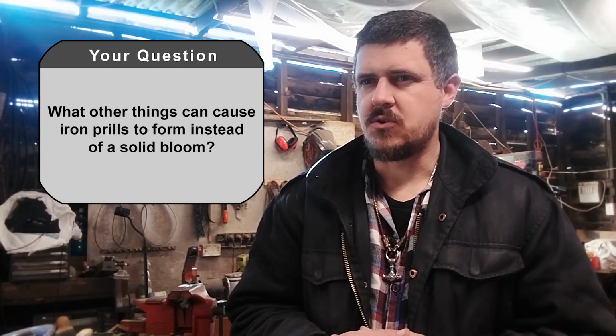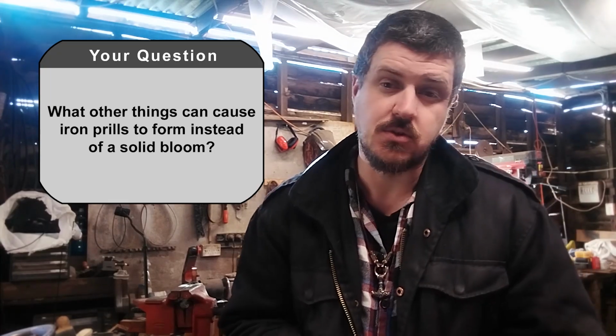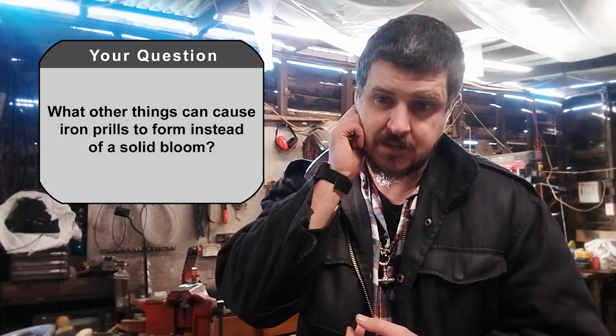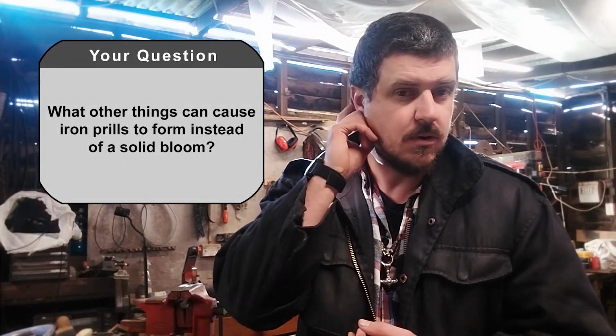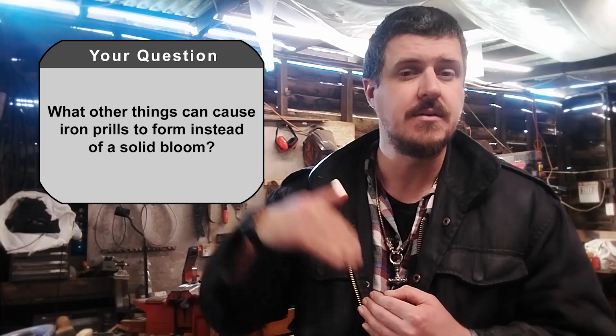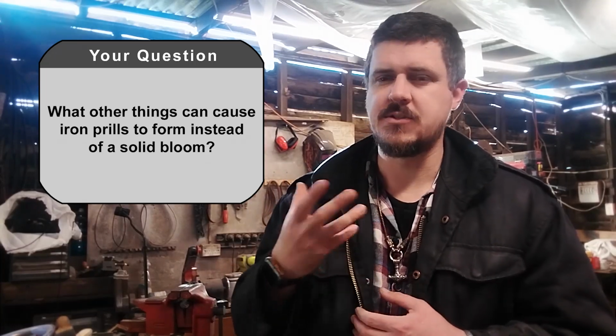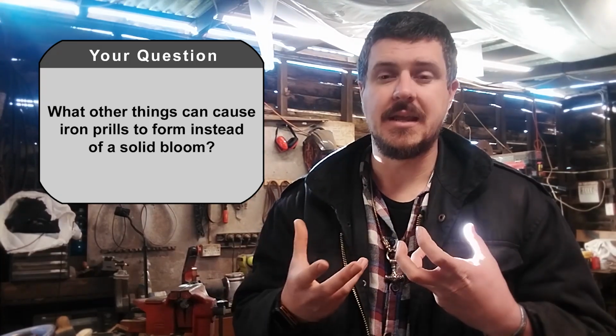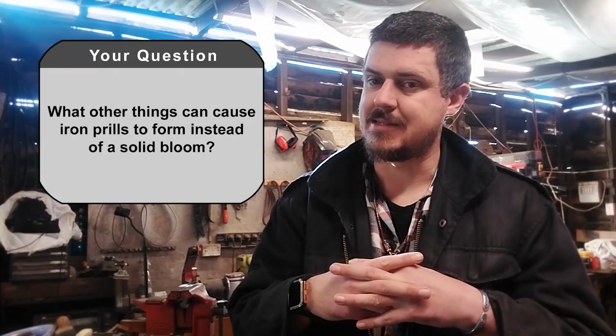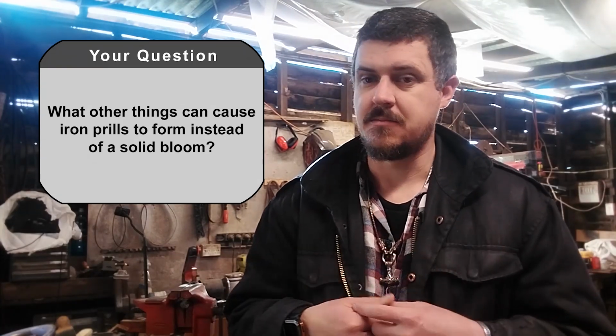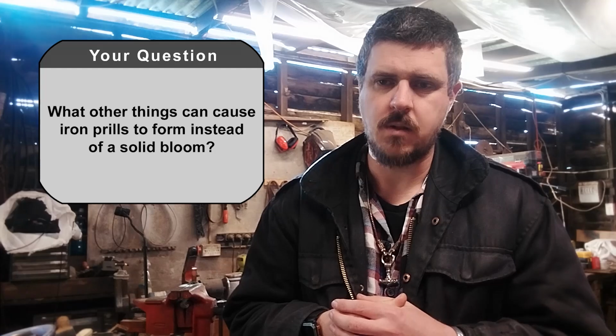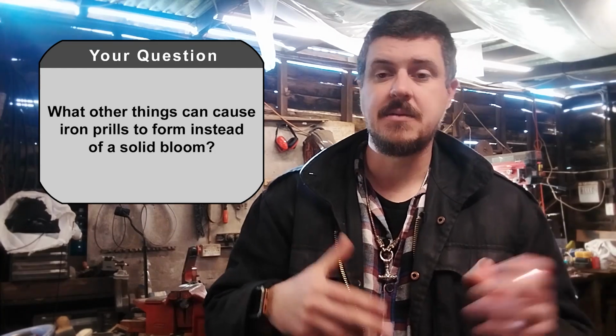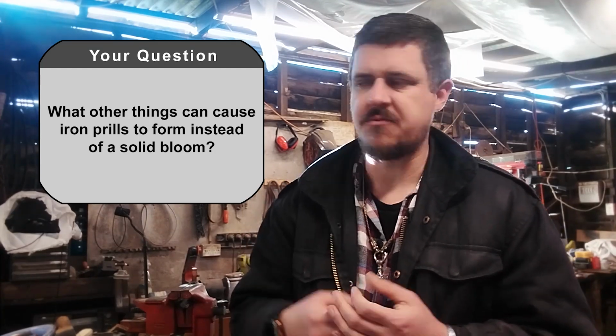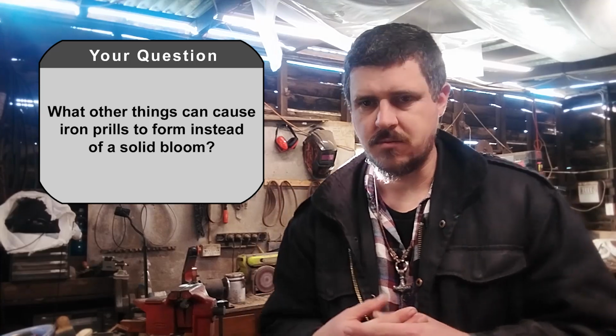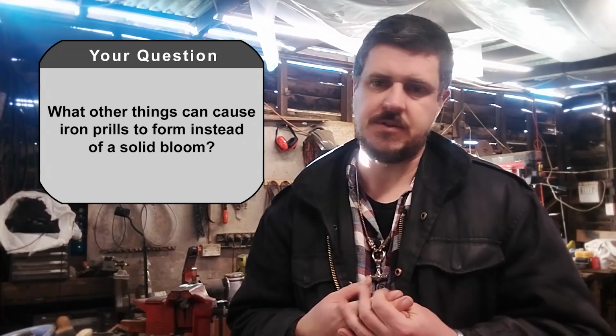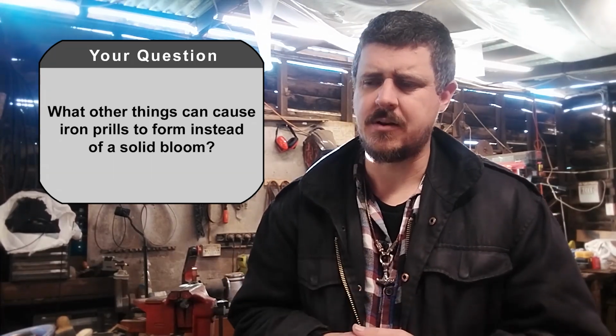Another one is that your charcoal quality is super low. If your charcoal quality is really bad, then you're not going to have effective reduction of the iron, and when the iron doesn't reduce properly, it can't coalesce properly, and if it can't coalesce properly, it can't sinter properly. So that's another big one to watch out for. So good quality charcoal matters, and ancient smiths would have known which trees to get it from, how long to age the trees for before charring them, what their process was for charring them, etc., etc.